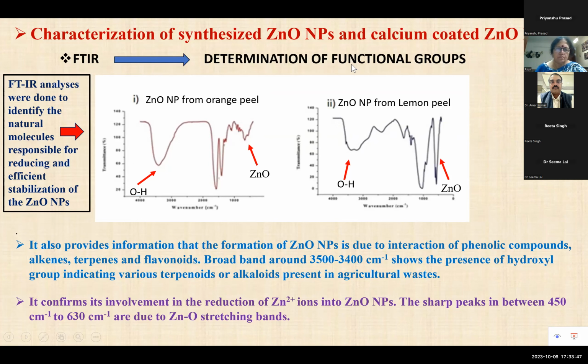Broadband around 3400-3500 shows the presence of a hydroxyl group, indicating various terpenoids or alkaloids present in agricultural waste. It confirms its involvement in the reduction of zinc 2 plus ions into zinc oxide nanoparticles. The sharp peaks between 450 to 630 are due to the zinc and oxygen stretching band.